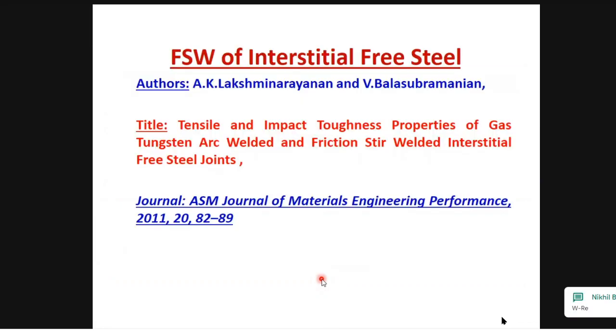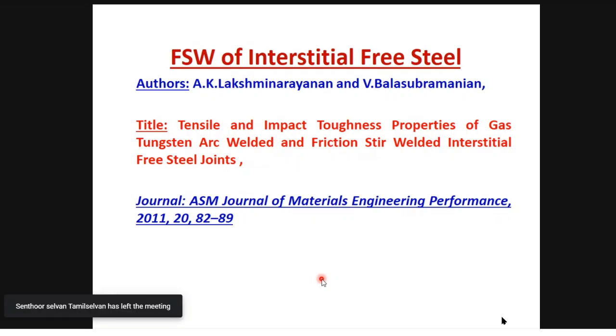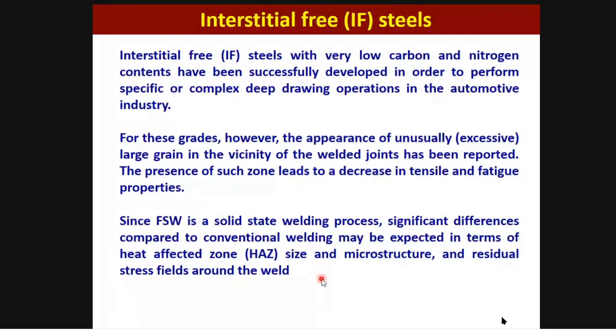So these are some of the precautions you have to take while joining these high melting temperature materials. I will show a few case studies of what we did in our center. The first one is interstitial free steel. Actually, we started with steel because it's easy. This IF steel is very easy to weld by the friction stir welding process because it has very high ductility. This work was done by Dr. Lakshmi Narayanan when he was doing his PhD here. And IF steel, you know, is interstitial free steel, with very low carbon and low nitrogen content.